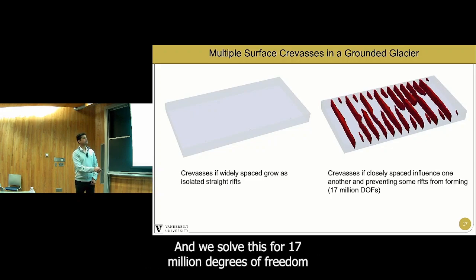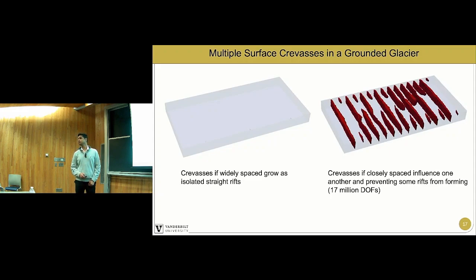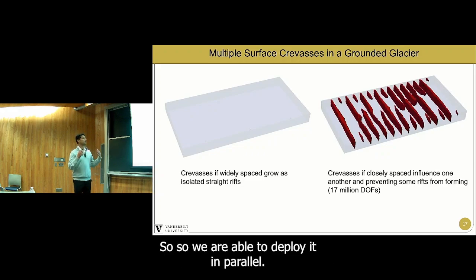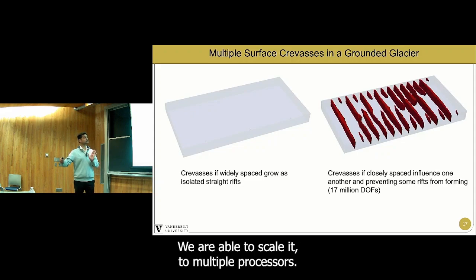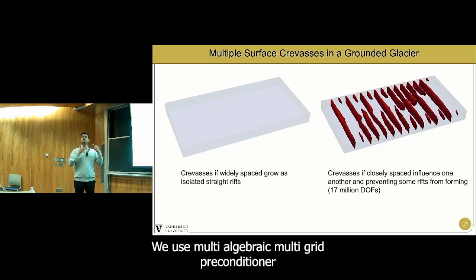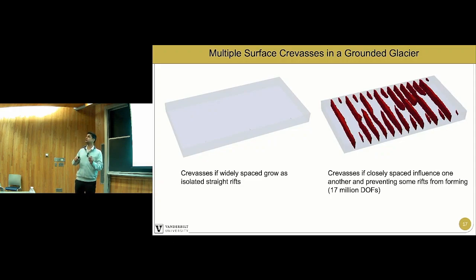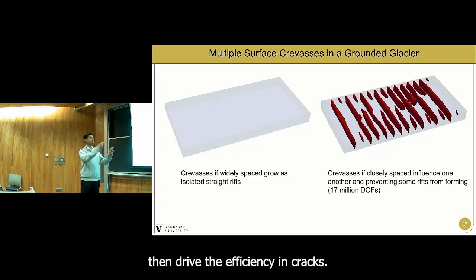And we solved this for 17 million degrees of freedom on just 40 cores. And this ran for less than 5 hours, right? So we are able to deploy it in parallel. We are able to scale it to multiple processors. We use algebraic multigrid preconditioners and iterative solvers in PETSc to drive the efficiency in cracks.